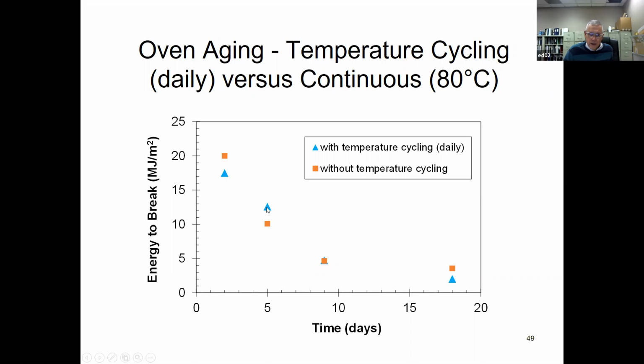And so we expected with temperature cycling to be lower. Here we use energy to break. Next week we'll see that sometimes there are advantages to using energy to break in place of elongation to break. So energy to break is the integrated area under the stress strain curve. So we're predicting this to be lower at every aging time, but yes, it's significantly lower here, but it's actually significantly higher here. Here, no difference. And then again, here it's significantly lower.